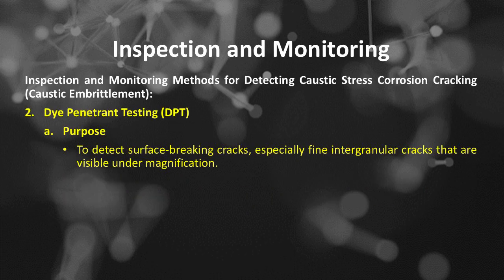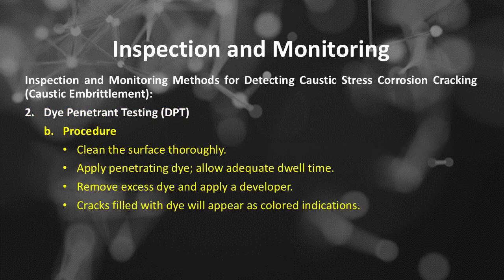Inspection and monitoring methods for detecting caustic embrittlement. Number 2 is dye penetrant testing or DPT. It is purposed to detect surface breaking cracks, especially fine intergranular cracks that are visible under magnification. Dye penetrant testing or DPT procedure includes: clean the surface thoroughly, apply penetrating dye, allow adequate dwell time, remove excess dye and apply a developer.